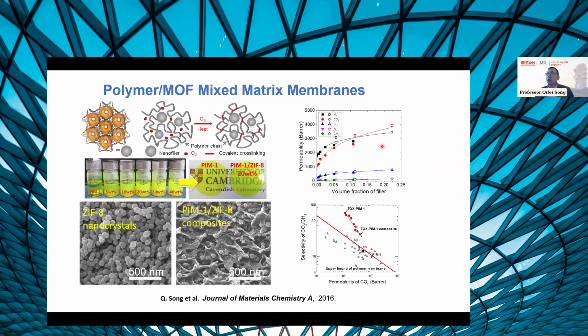Based on this work, we also developed polymer MOF mixed matrix membranes. As many of you are aware, MOF-based mixed matrix membranes have a lot of advantages compared to traditional materials, because potentially they can combine the properties of the MOFs, including the molecular sieving properties, and the polymers. So in this study, we combined the PIMs and the MOFs and developed the mixed matrix membranes. We also cross-linked the PIMs, so we got really high permeability and selectivity. The MOFs function as fillers that can enhance the gas permeability.